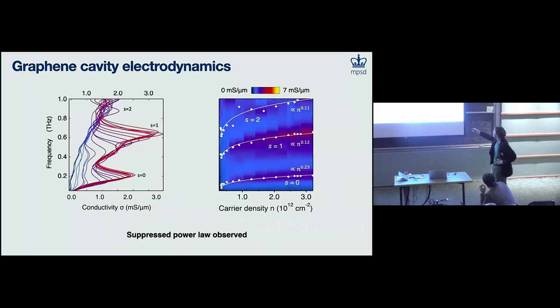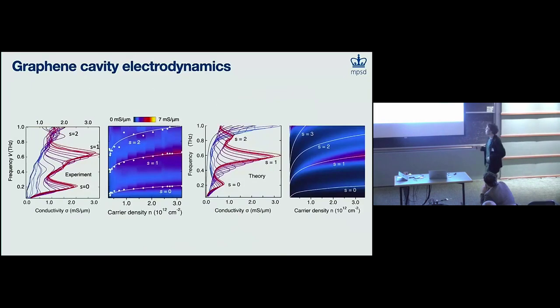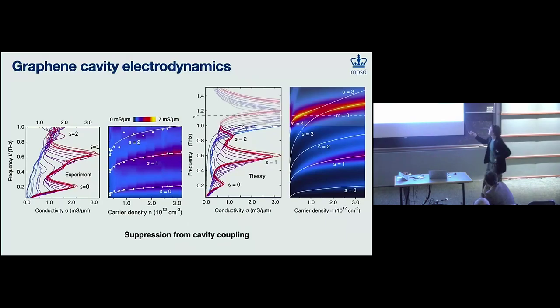But what we find is that when we look at these higher order resonances, the scaling is heavily suppressed from what's expected. So we didn't understand this, and so we worked with Marios from Angel's group, who over the course of a couple of years, really working intimately with us over many, many devices and iterations, developed this wonderful analytic theory to predict what you should see in an on-chip terahertz experiment. And you can see that his theory agrees pretty well with what we measure in experiment, including the suppressed couplings. But what's nice about the theory is that it's just in Mathematica, so if you want to see what's happening at higher frequencies, you just go to higher frequencies, and you can see what happens when the graphene modes intersect the graphite cavity mode, that they are in fact hybridizing, approaching the ultra-strong coupling regime. And one of the consequences of this hybridization up here is the suppression of these other polariton branches in their carrier density scaling.